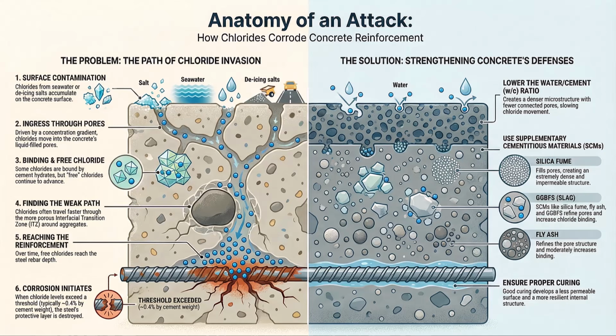Not at all. However, with the mandated SCM combinations, GGBFS plus silica fume, and a low water-to-binder ratio, the achievable real service life increases dramatically. We're pushing targets out to 80, 100, or even 120 years. This leap in durability is absolutely non-negotiable for supporting the long-term economic development goals in the GCC.